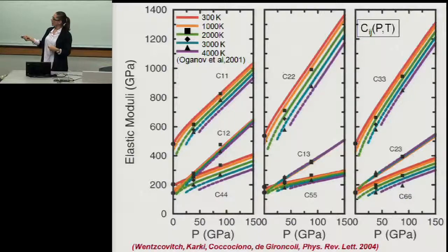Okay, here are elastic constants of perovskite that we obtained in 2004, continuum of pressure temperature using the quasi-harmonic calculation. These black points were obtained by Oganov and collaborators using molecular dynamics. And to me, the agreement was surprisingly good. I did not expect this level of agreement, but they obtained the elastic constants at certain temperatures between 1500 Kelvin, 2500 Kelvin. And these points essentially fall in between the appropriate colored lines.